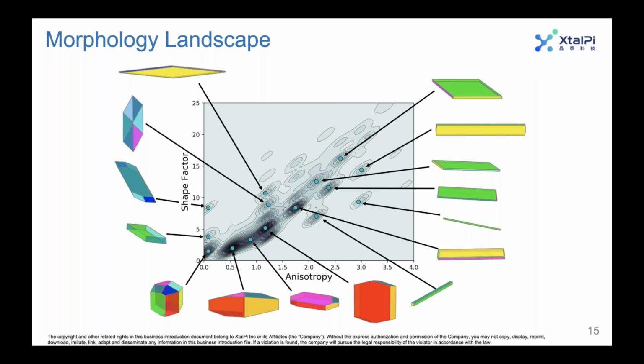Maybe you would see that with a very high aspect ratio crystal. Based on the lattice, it might be predetermined to form needles. That would be unfortunate, if we found that the experimental variables can't change the morphology, but that in and of itself would be a useful result, right? Because presumably you would have performed some experiments too, where you were only obtaining needles, and then you would have this modeling data that would suggest that only needles were possible. That would basically tell you that you're stuck with needles, and you can move on to trying to mitigate the morphology or planning ahead for your process that you're going to have to do some sort of downstream processing. And you would have both the experimental and the modeling data to back up that decision. So hopefully it would allow you to plan accordingly. Even though it's not necessarily the result you would want, I think it would be important for guiding your decision making nonetheless.